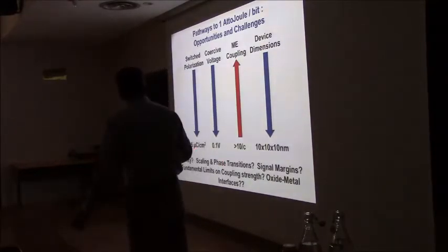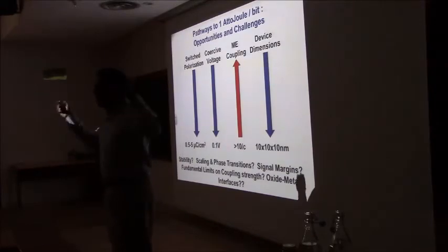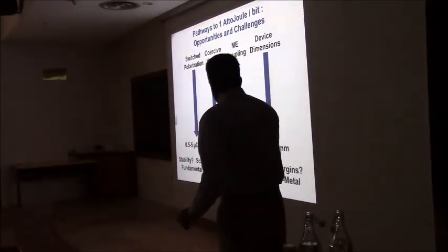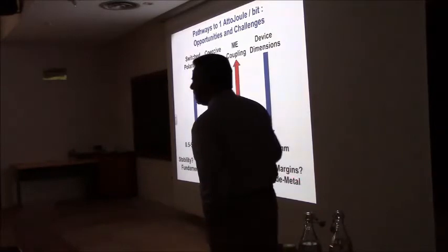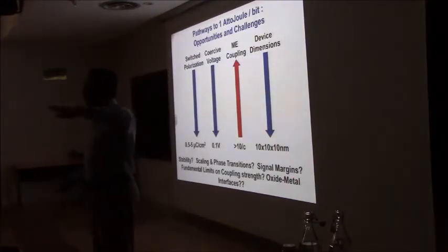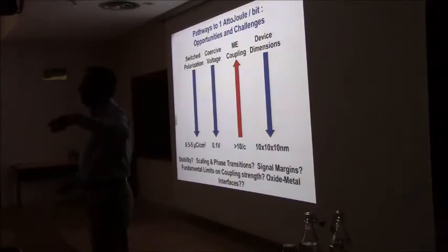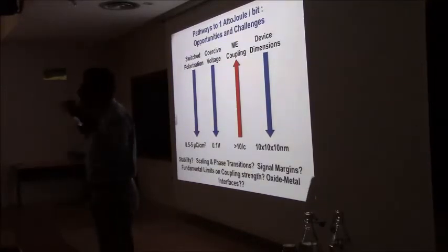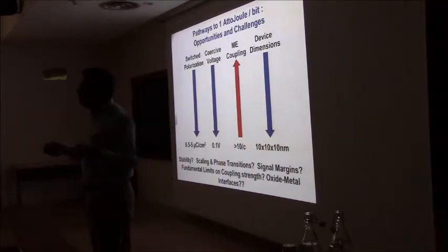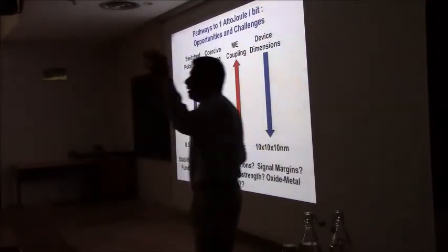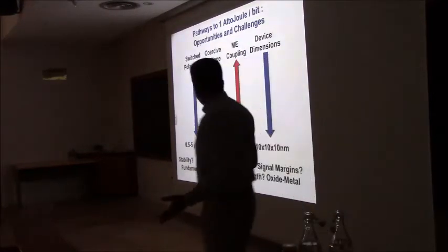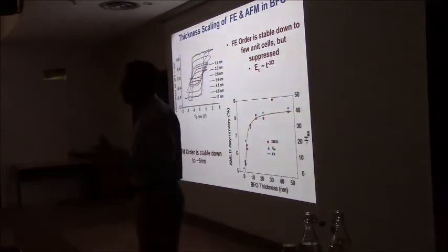Stability is clearly one of them. Scaling and phase transitions, we're not as worried because there are no fundamental phase transitions at the 10 nanometer scale. Signal margins depends on this for sure. Limits on coupling strength, I think this is the one which is going to be the killer. The interface between the ferroelectric oxide and, if you're going to use a ferromagnetic metal, you're going to have problems because that's typically a Schottky barrier. And lots of crazy things. So the entire physics of polarization fatigue in ferroelectrics that we solved 25 years ago was by using oxide electrodes, for example. That's going to show up here again. So there's a big challenge for all the people doing materials physics, new materials, in terms of what is that ferromagnetic metal.